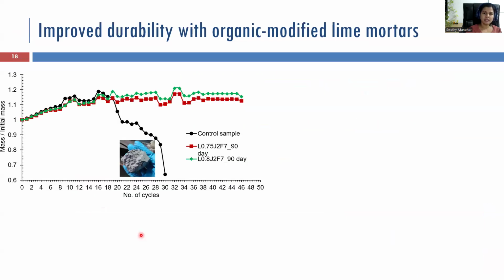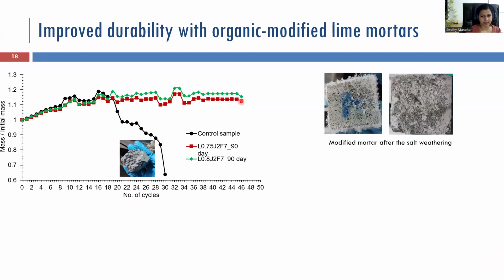When we subjected the samples modified with organic and without organic to artificial salt weathering, we saw that the black line, which is the control sample - lime sample without organic - failed at around 25 to 30 salt weathering cycles. But when we had jaggery in the system, it was performing well even at a larger number of salt weathering cycles.